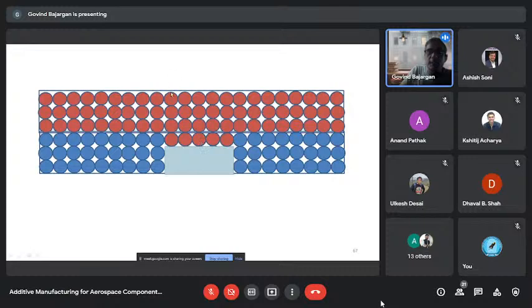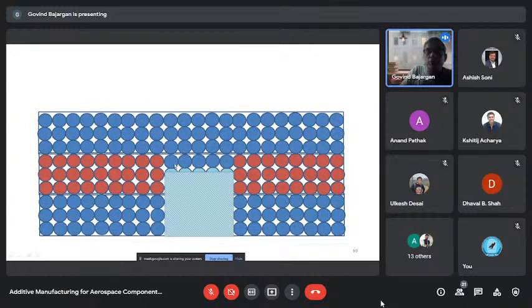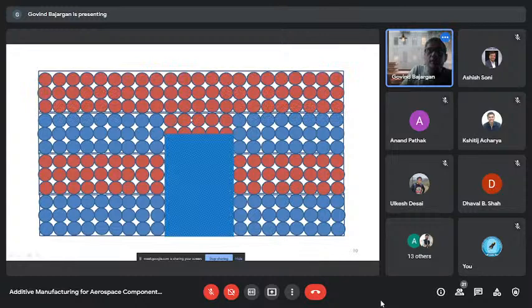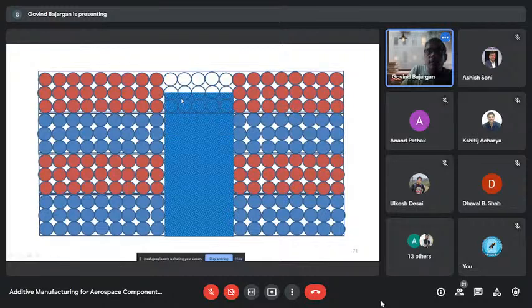Now the next time the laser has to come here, it has to melt not just one layer, it has to melt powder more than a layer. Also, it has to melt part of the base metal so that bonding can happen. So it continues. Now, when it is melted, we have an unmelted zone which is more than one layer of spheres. Again, the laser has to melt this much powder and the base of it, so this much amount of energy will be required. Then the powder layer height has become 1.5 times the thickness; instead of one powder layer, it has become 1.5. Now the laser has to melt 1.5. So this way it continues.